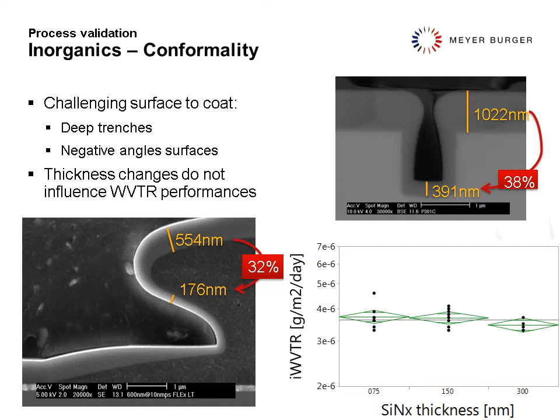Now the second question that arises immediately is, okay, we decided to coat, for example, 500, 1000, 300, whatever thickness. Will then the limited amount of thickness that is coated on these special surfaces be enough? For that reason, we had a look at the intrinsic WVTR at thinner layers. So we went down to 300, 150, and 75 nanometer, and we could find consistently that these layers were able to match the expectation. Now, this scale is logarithmic, and what you see is that basically there's no difference. They all perform in the same way. We're all in the 10^-6 region.